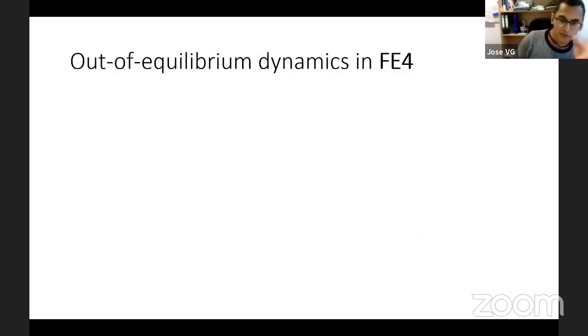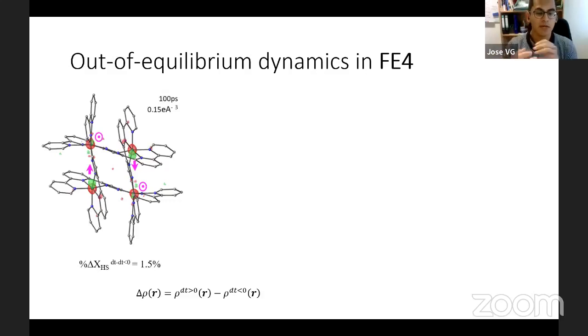So we talked a bit about this in my last presentation. The out of equilibrium dynamics in the totally connected grid, the so-called iron 4 grid: when we photoexcite, we have a structural response that we can track using photodifference maps. A photodifference map is the difference between the electron density of the excited state and the ground state. It creates maps where the red area indicates where the metal ion used to be, and the green areas are where the electron density has shifted after light excitation.